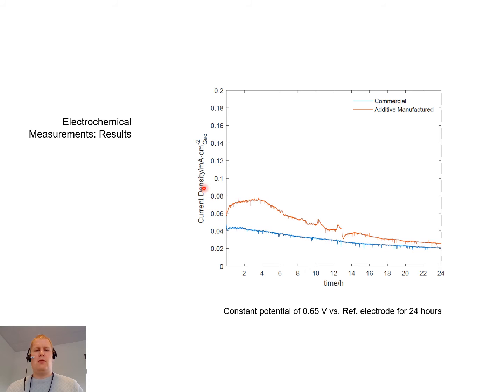The current here is normalized by the surface that was exposed to the electrolyte, in this case 3 square centimeters. As you can see here, the current density of the additive manufactured sample is always higher than the commercial sample. This indicates a higher corrosion of the additive manufactured sample, since we can assume that there is a direct correlation between the current and the corrosion rate.